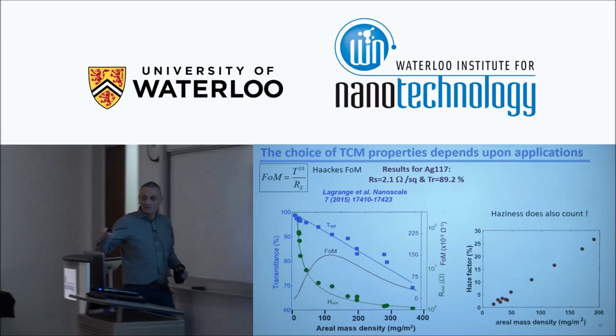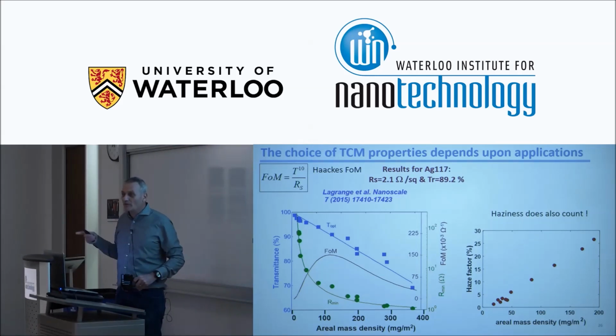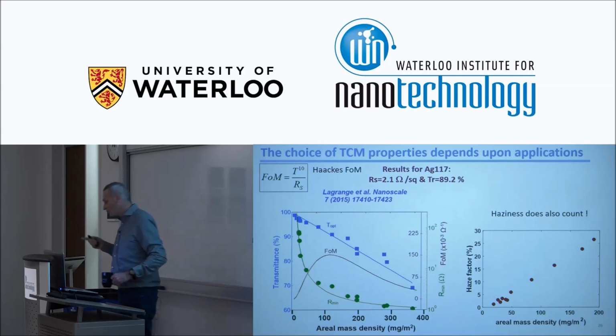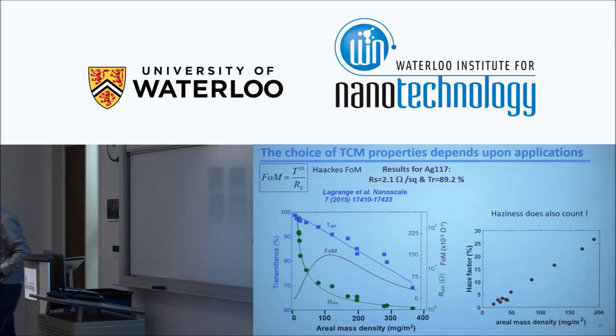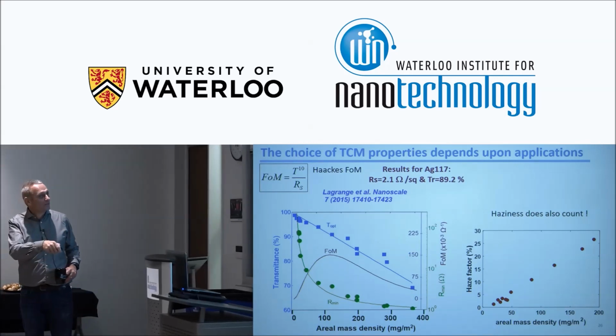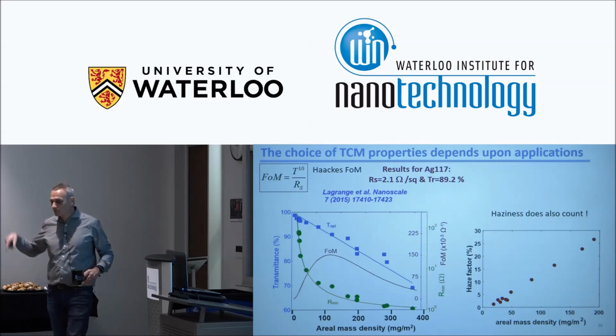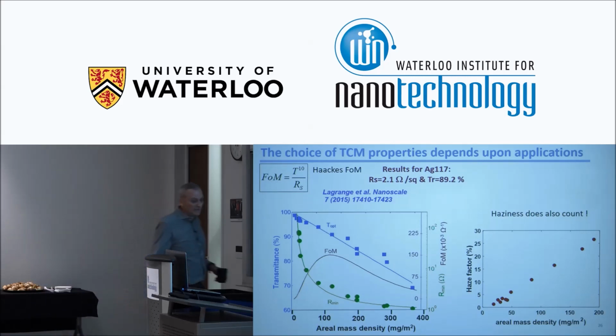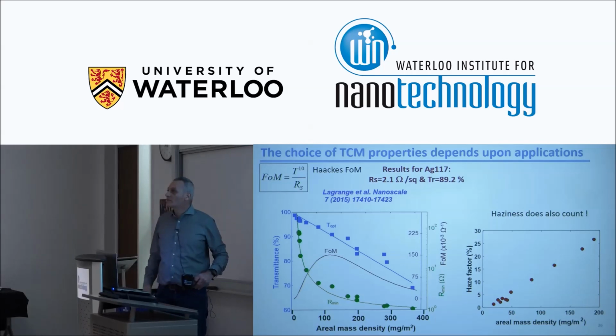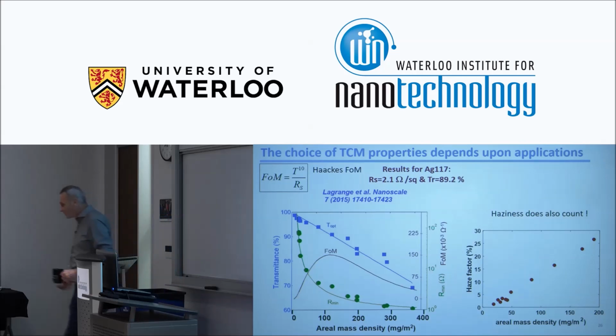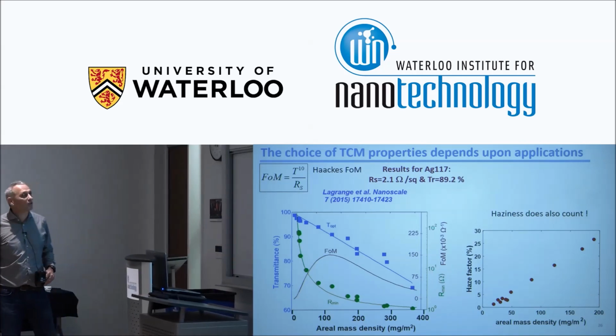So if you put 1 kilo of silver on the table, the chemists are able to give you 500 grams of silver nanowires. And if we don't waste some, it will not be 100% efficient, but if we are using these 500 grams to deposit some silver nano networks with a density of, let's say, 100 milligrams per square meter, with 1 gram, we can make 10 square meters. So with 500 grams, we can make something like 5,000 square meters coming from 1 kilo of silver. I know it's not 100% efficient, but that means the cost should be rather low, okay? Even if silver is an expensive material.